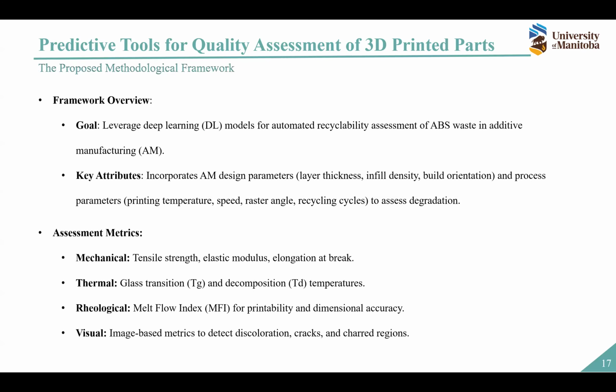So we're going to propose our methodological framework. Our goal is to use deep learning models for automated recyclability assessment of ABS waste. The key inputs are design parameters like layer thickness, infill density, and build orientation, and also process parameters like printing temperature, printing speed, raster angle, and recycling cycles to assess the degradation. What are going to be the outputs of our deep learning? The assessment metrics, which are mechanical and thermorheological properties, and also visual properties like the crack distribution and the char region are included here.